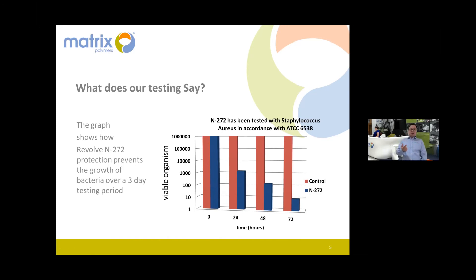In the next 24 hours the bacterial count on the antimicrobial sample continues to reduce, while on the reference polymer the numbers grew. What does this mean in practice? If you have an antimicrobial table or chair, you don't have to clean it every day — it essentially self-cleans. You could probably just do it once a week.